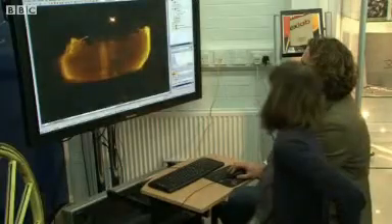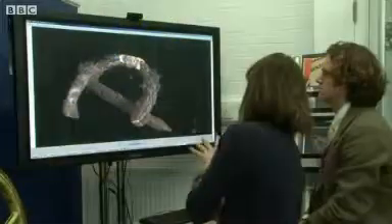This is definitely metal. Which is incredibly exciting because here you can see very clearly, you can see the copper alloy go up behind the iron section. The benefits of seeing this virtually before you start excavating the object is that as you excavate, the cauldron becomes very unstable, the metal's very, very thin and very mineralised. So as soon as you start taking the soil away from around it, there's nothing else supporting it. And the cauldron will eventually have to be taken out in fragments and probably never be whole again.